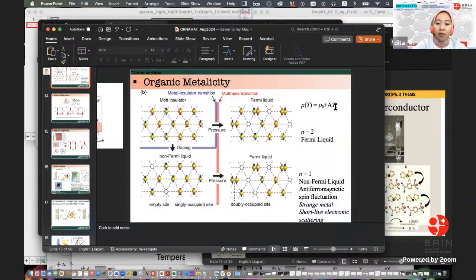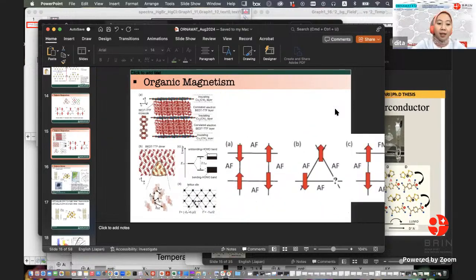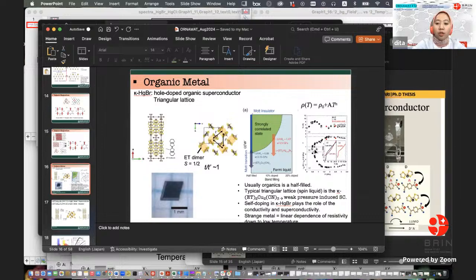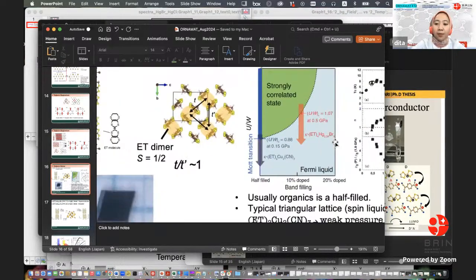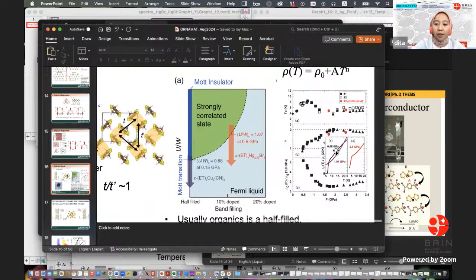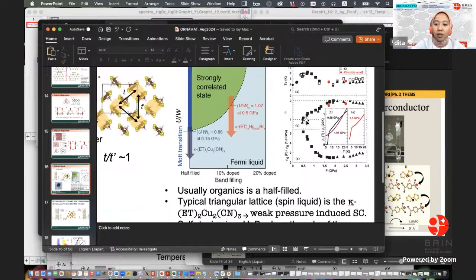The metallic state of the cuprate superconductor shows T linear, so n is 1. So that is the first phenomenological resistivity measurement indication that it's clearly not a Fermi liquid, right? And then in our case, we can also see such behavior. Here you see n equal 1 for 0.48 gigapascal. You can see it's clearly linear like this, right?